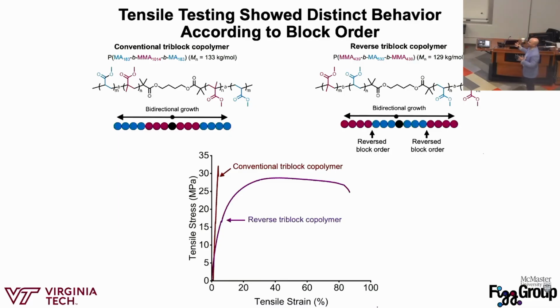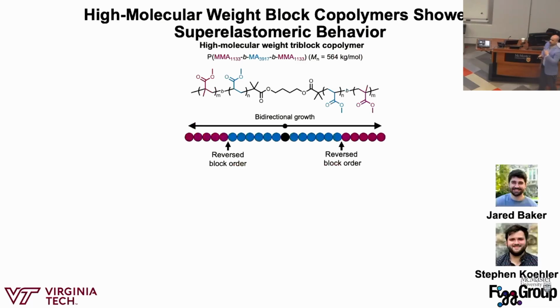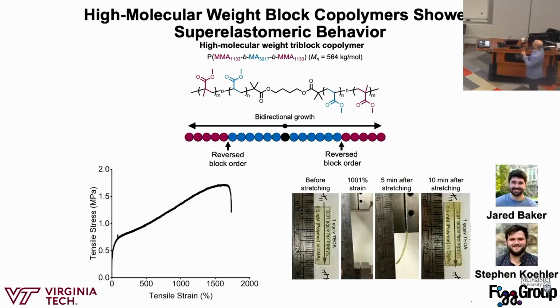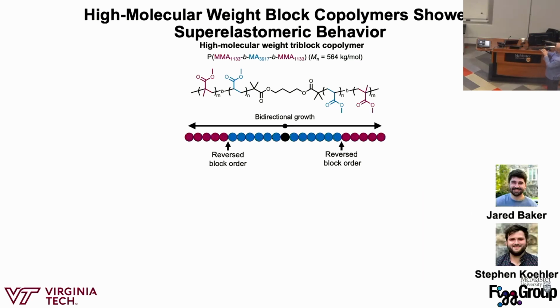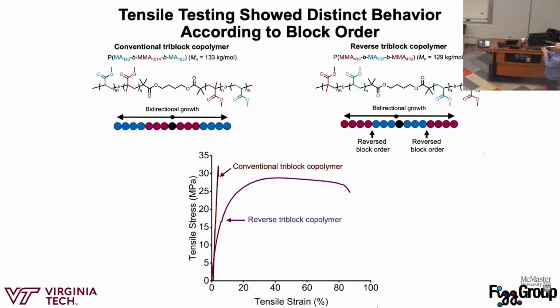So these properties are expected, but this type of structure is very hard to synthesize using a lot of controlled polymerization techniques. The advantage that RAFT polymerization has over any other polymerization technique, except for maybe anionic, is that you can synthesize really high molecular weights. So in this case, we did our chemistry to synthesize a polymer that was 564,000 grams per mole, again with our reversed order. And so now this is like 5 times bigger than the last polymer that I showed you, and then we did tensile testing to see the effects. And what's really cool here is that this reverse one, we're going to about 1700% strain, and then it breaks.